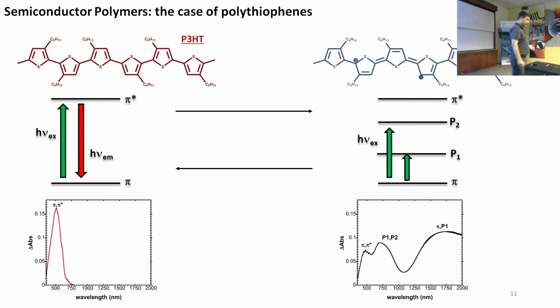The consequence of this is that the absorption spectrum, because now you have these electronic transitions, is pushed into the near-infrared region, while the absorption of light in the visible region decreases a lot, and so the spectroscopic signature of this material changes. Also, the color decreases because the color in the visible region disappears. It appears in the near-infrared region.